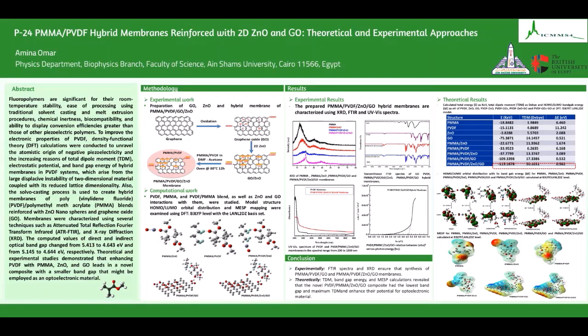And from the results, we ensure the presence of polymethyl methacrylate PVDF graphene oxide hybrid membrane, and also polymethyl methacrylate PVDF zinc oxide graphene oxide hybrid membrane. And from theoretical results, we have the total dipole moment and the band gap energy and the molecular electrostatic potential calculation reveals that the novel structure of the polymethyl methacrylate PVDF zinc oxide graphene oxide composite has the lowest band gap and the maximum total dipole moment, which enhances the potential for optoelectronics material.